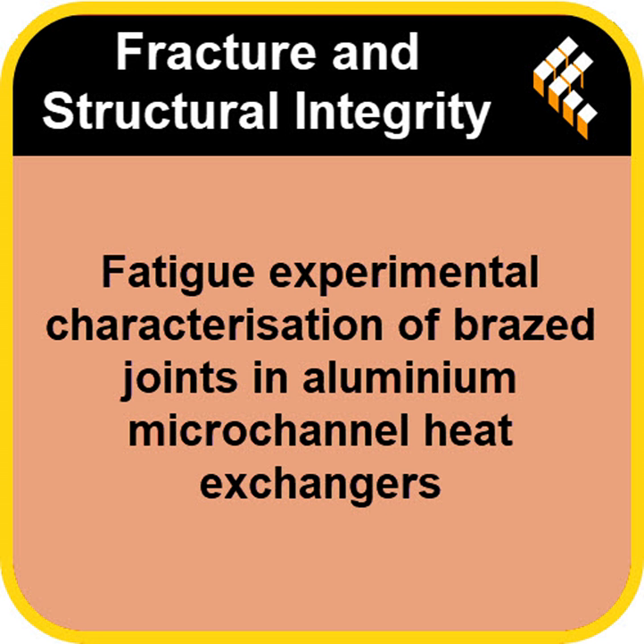Okay, so the simulation predicted the failure spot. The fatigue test confirmed the joint is the weak link with the specific endurance limit. Now, let's get to the microscopic evidence. The smoking gun, perhaps? Right. They used scanning electron microscopy, SEM, to look closely at the fracture surfaces of the failed fatigue specimens. Fractography. And did the physical evidence line up with the computer model's prediction? Did the cracks actually start where the FEA said they would?